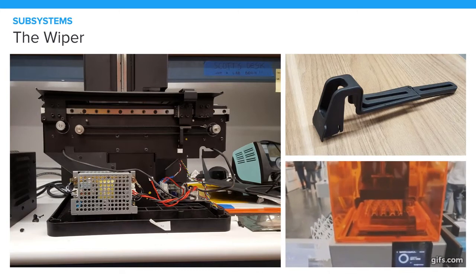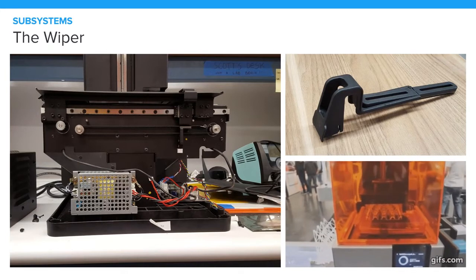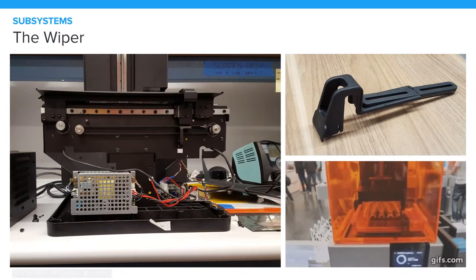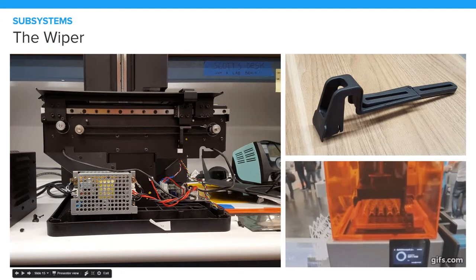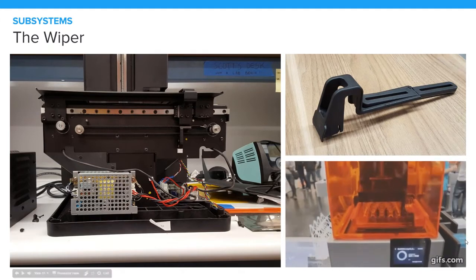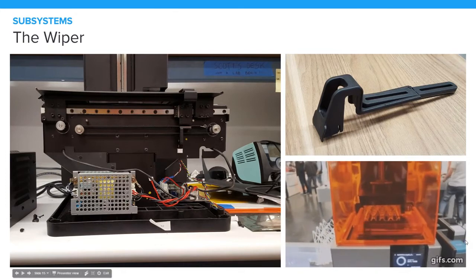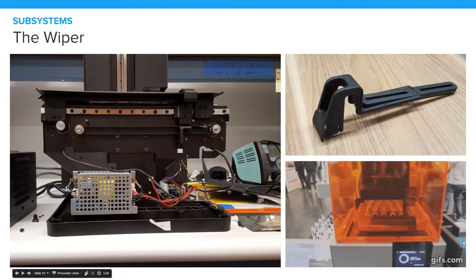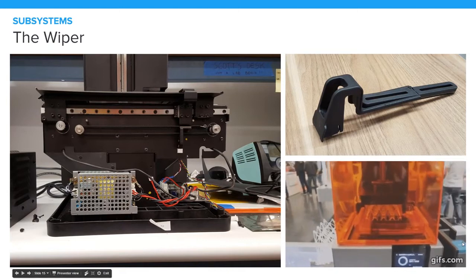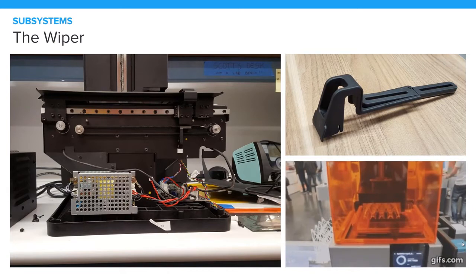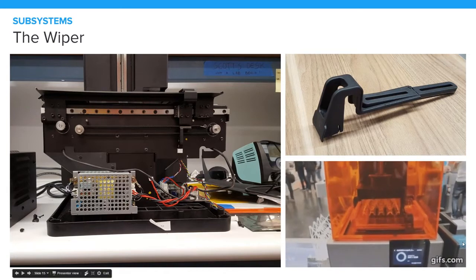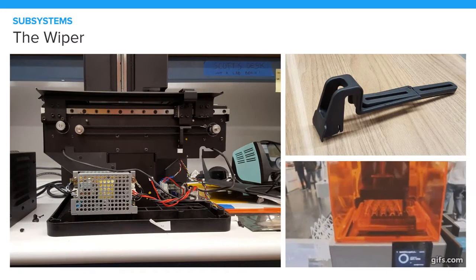So when the part's being pulled away from the tank, the PDMS layer at the bottom of the resin tank actually flexes slightly to allow that to move. The wiper's main purpose there is to stir the resin so it maintains a constant consistency that prevents gooping or globby resin spills on your parts. It also removes any bit of resin that might be stuck on the PDMS, and then finally, when I say it oxygenates the PDMS, it's basically exposing this layer of silicone to the air so it can soak up some of that sweet, sweet O2. That allows the print, when the part cures, to actually cure slightly above the PDMS, on top of that oxygen layer. So that's one of the big reasons that we include the wiper, because it reduces peel forces and increases print reliability.